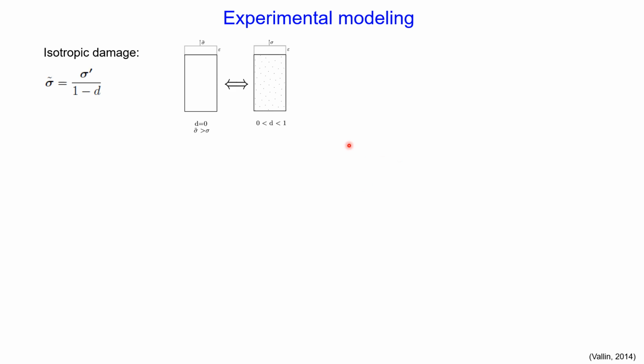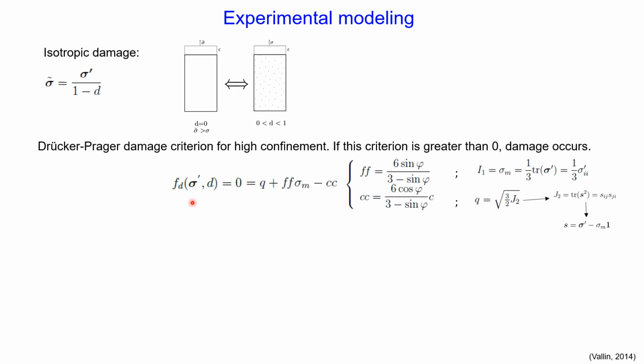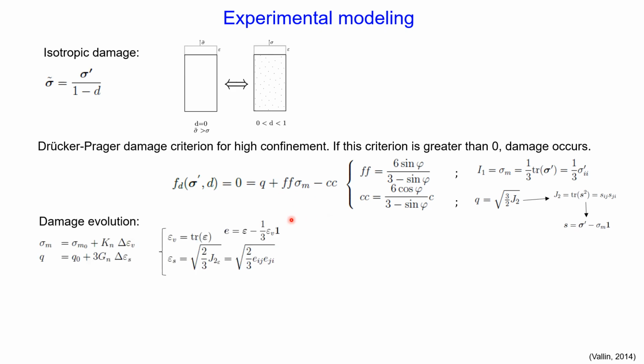For this case, we consider isotropic damage, which allows us to express the damage as a function of a single variable d. A damage criterion is introduced through the definition of a yield surface in the stress space. This model adopts a Drucker-Prager criterion. Finally, the mean and deviatoric stresses are evaluated from the imposed deformation and the homogenized moduli.